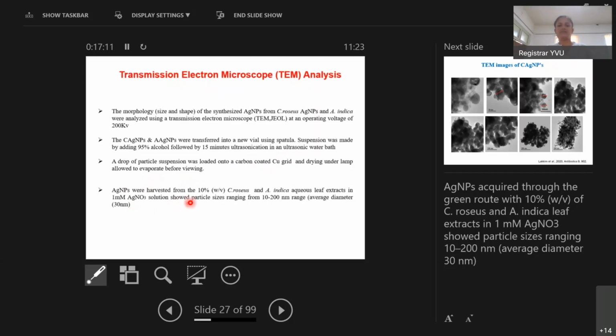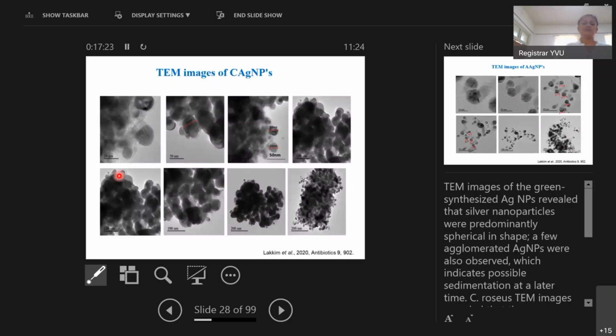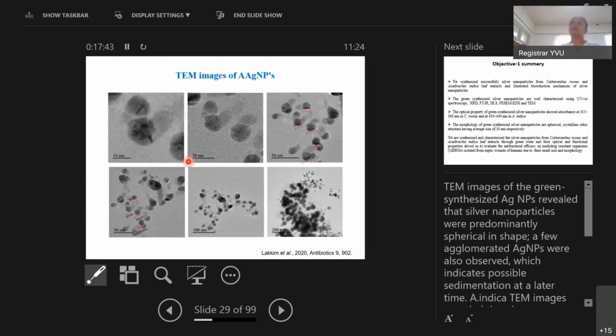These AgNPs harvested from 10% show different particle sizes ranging from 10 to 200 nanometers. The average diameter is 30 nm. These are the different magnifications: 20 nm, 50 nm, 100 nm, and 200 nm. The average particle size is 30 nanometers in Catharanthus roseus silver nanoparticles. These transmission electron microscopic images clearly show the diameter of Catharanthus roseus silver nanoparticles, and these are the transmission electron microscopic images of Azadirachta indica, particle size 13 nanometer with a spherical shape, which is clearly shown.